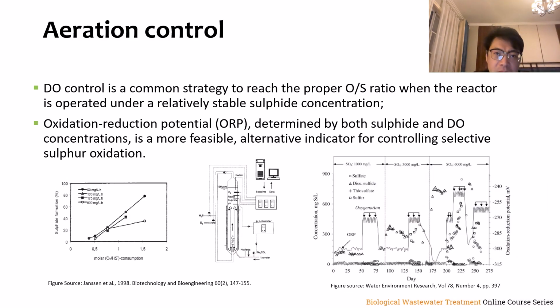And in these slides, I'd like to dive into the challenges and strategies involved in maintaining the optimal oxygen to sulfide ratio in bioreactors, particularly focusing on the role of dissolved oxygen control. Maintaining the proper O/S ratio is crucial for efficient process operations, especially when dealing with processes like sulfur oxidation in bioreactors. A common strategy employed to achieve this is the control of dissolved oxygen within the reactor. This approach is particularly effective when the reactor operates under a relatively stable sulfide concentration, allowing for consistent and predictable reactions.